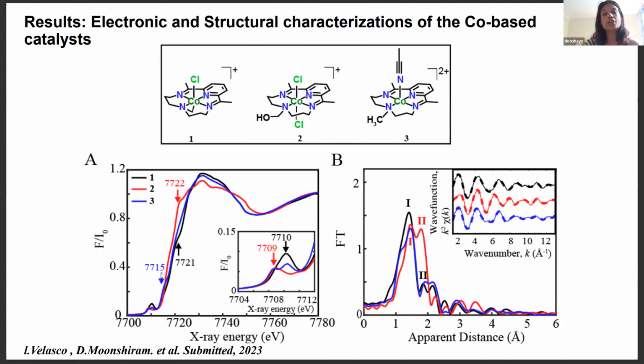All free catalysts show a rising edge which is different. So for example, if you look at catalyst 1 and 2, it has a 1s to 4p plus shakedown transition along the rising edge. These shakedown transitions correspond to ligand-to-metal charge transfer states due to relaxation of the cobalt local electrons in the excited states, and are highly dependent on the metal-to-ligand covalency as well as the donor character of the ligand.